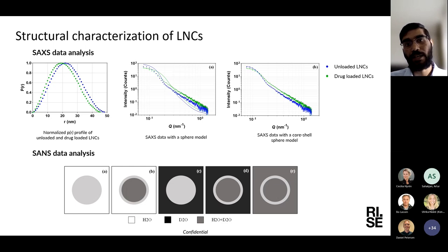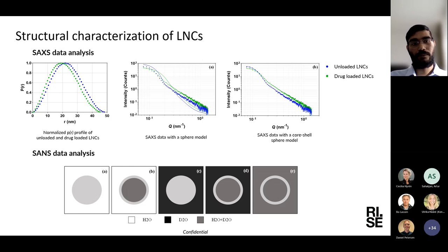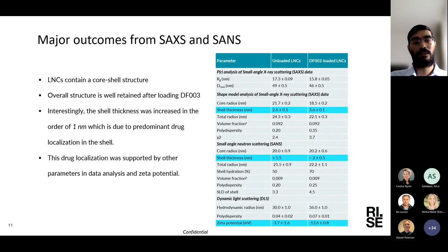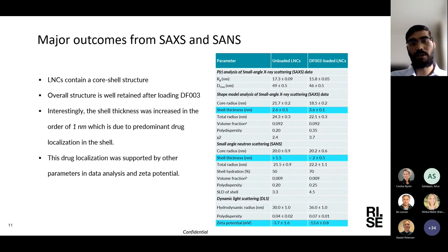Interestingly, the core-shell structure is retained both for drug-loaded and unloaded particles. For the neutron scattering experiments, we prepared a series of samples with different contrasts in the core and dispersion medium to visualize different parts of the nanoparticles. The outcomes from SAXS and SANS confirmed the particles have a core-shell structure well-retained after drug loading. Upon drug loading, the shell thickness increases on the order of a nanometer, predominantly due to localization of the drug on the particle surface. This was supported by zeta potential data: unloaded particles have a slightly negative zeta potential, while drug-loaded particles show a more negative zeta potential, confirming the drug sits on the surface rather than in the core.